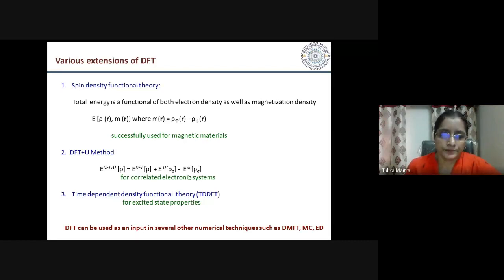Then for correlated materials, it is seen that the correlation that is incorporated in the traditional density functional theory is not enough to account for the correlation. So we have to explicitly add that correlation term in the energy functional, and then we have to subtract also, because there was already some part of the correlation in the basic density functional theory, and we are adding explicitly some extra correlation. So in order not to have double counting of the correlation, we have to subtract this part. Okay, so this method, DFT plus U method, is used for correlated electronic systems, which can give you the correct ground state electronic structure, or the band gap and all can be calculated using this DFT plus U method.